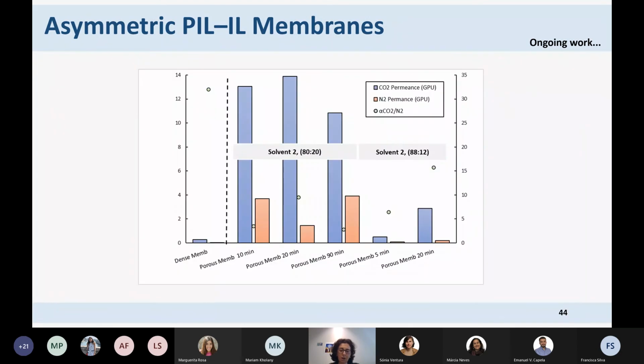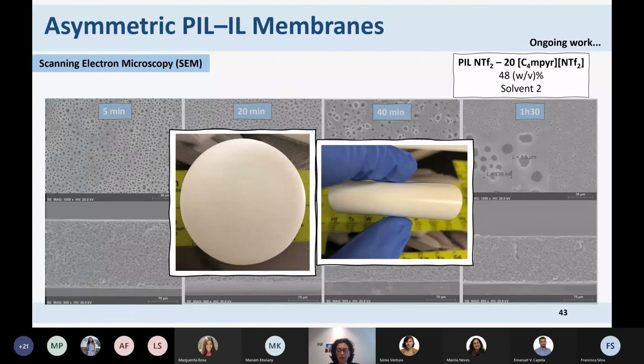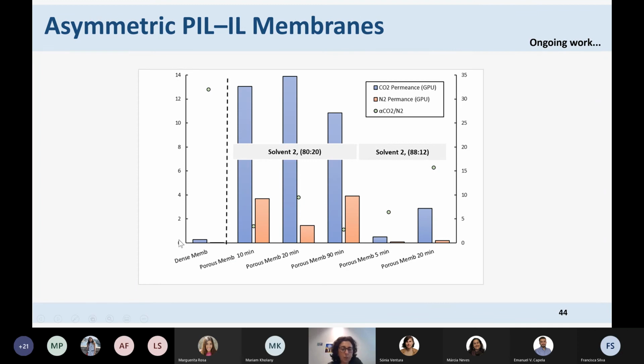But these membranes are flexible, they don't break. And so we can measure the permeability of these membranes. So we have here the comparison for CO2 and N2 of the dense membranes and the porous membranes that I've been talking to you about. This is always solvent two, and this is the ratio to the non-solvent, okay? And what we can see is that the permeability is much larger, of course, because they are porous, and so the gas just flies through.